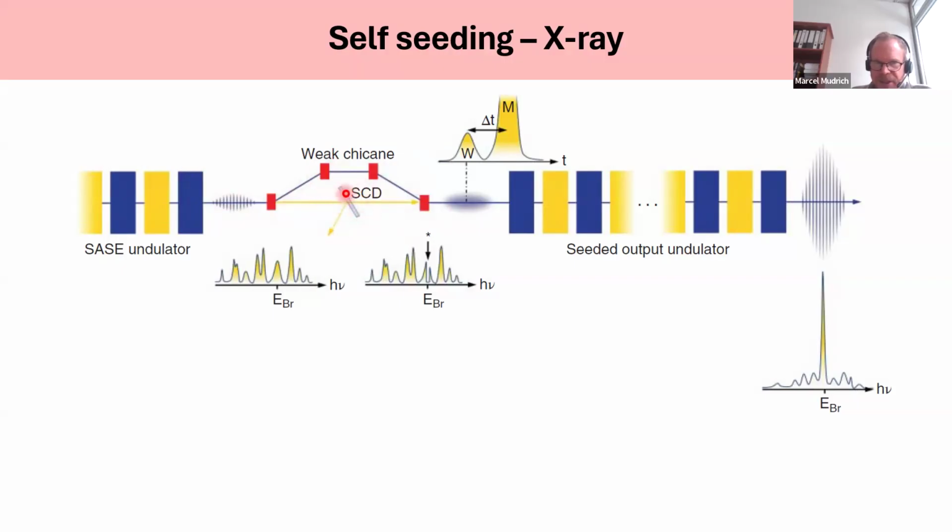In this case, for X-rays, as I said, it has to be a grating with angstrom lattice constant. So this is just a single crystal diffraction device. It's basically a thin single crystal, usually diamond, a thin diamond plate, which is used for monochromatizing the pulses.